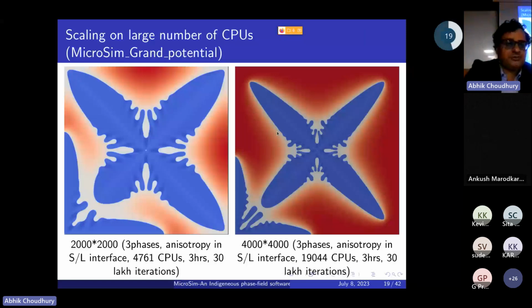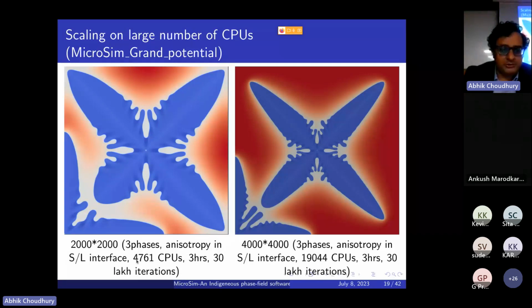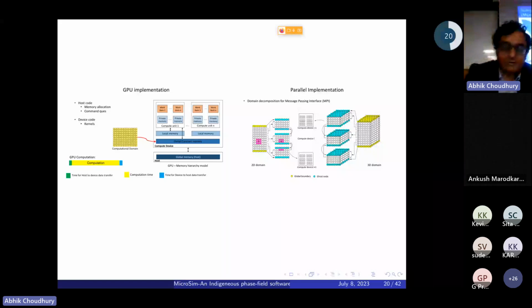So one of the things that our solvers are capable of, particularly the MPI solvers, is that they scale very well. Just to show you briefly, the left simulation is performed with 4 million points, and on the right is 16 million points. The left simulation was launched with 4761 CPUs on the Param Vega machine, and on the right is the same type of simulation, but 4 times larger. We utilize four times the number of CPUs, and you can get the same number of iterations done in the same time, which essentially shows that the system is scaling, and you can use a large number of CPUs for these calculations.